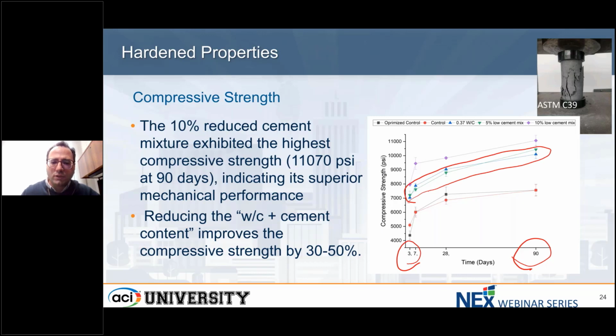But something I want to highlight here is the performance of the low water cement ratio, 10% reduced cement one, shown here in purple. As you can see, at early ages and long term, it performs superior compared to all other mix designs. Later on, we're going to discuss that the main reason for this is the reduction of void content, or improving the packing density of the system in this type of mixes. We see almost a 30 to 50% improvement when comparing this mix design with the control mix designs.